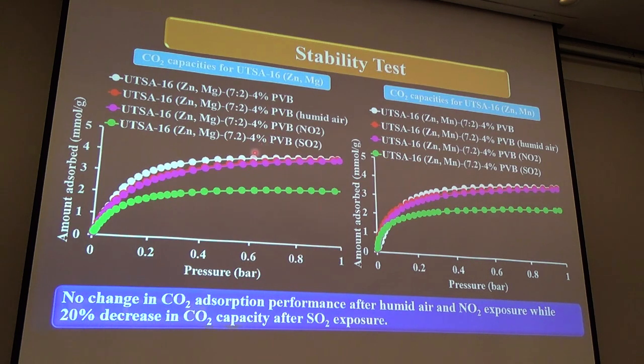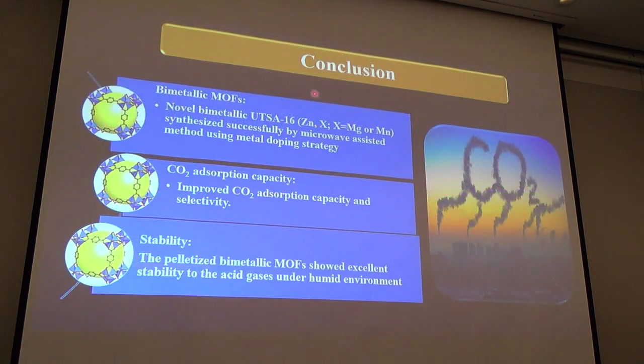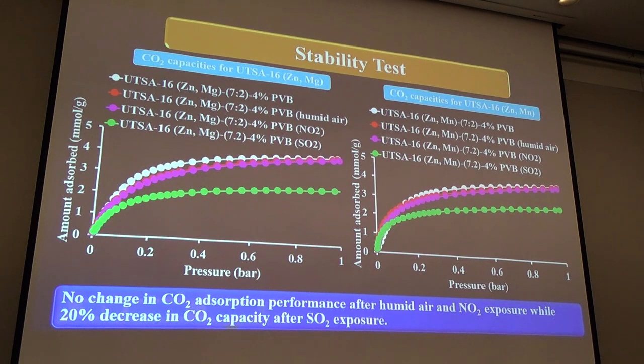As a concern of practical application, we pelletized the bimetallic MOFs and studied them for stability by exposing them to acid gases and humid air. As we see, there is no change in adsorption capacities after exposure to humid air and nitrogen dioxide. However, a 20% decrease in CO2 adsorption capacity occurs after exposure to sulfur dioxide.